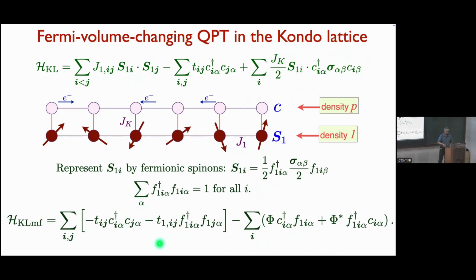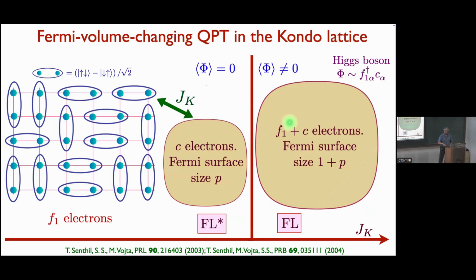You'll just get two bands, the bands of the c's and the bands of the f's, and they will hybridize with this phi, which is really a Higgs boson, which carries the gauge charge of these spinons. So when phi condenses, effectively the spinons become electrons, and you just get a two-band model. And if only the lower band is filled, by the Luttinger theorem, the area of the Fermi surface should be 1 plus p. And if phi is 0, then you get the FL star state. And many papers have been written discussing this phase transition, which I won't do now. So that's the basic phase transition between the FL star state and the Fermi liquid state in the Kondo lattice model. Well, it's just the condensation of this Higgs boson, which is the hybridization of the f and the c.